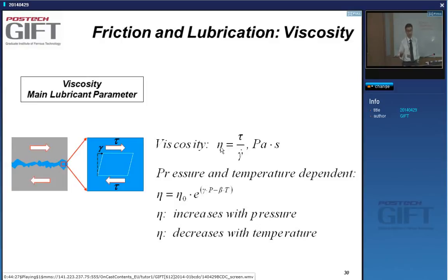We know that if you have an oil and you warm it up, it will become thinner. It will lose its viscosity. So the viscosity decreases with increasing temperature. What we usually do not know from experience is the fact that with pressure, the viscosity increases. All right. And of course, why is this so important? This is so important because in rolling, we have very high pressures.